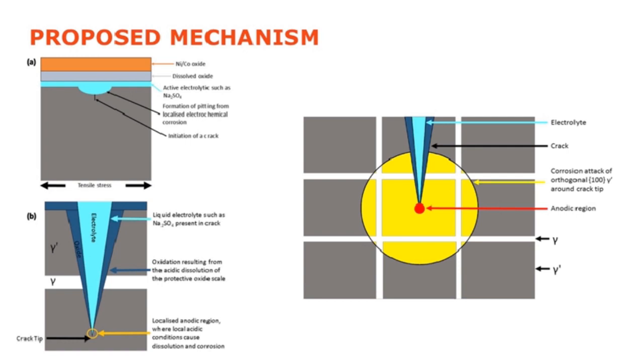But what we see is typical hot corrosion type features. So we've got a nickel cobalt oxide. Below that, we've got dissolved oxides, and then below that, we see kind of an electrolyte. And I've put sodium sulfate there, but I think again there's a number of compositions that electrolyte could be. So we then see formation of a pit or a crack, kind of locally. Again, I don't think there's any definitive way. I don't think it's a pit and then a crack or a crack and a pit. I think it probably just depends a lot of the time. And if we move down then to image B, in terms of how this sort of electrochemical circuit gets set up in the crack.